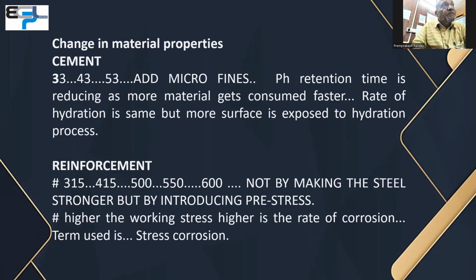There are microfines: microsilica, fly ash, GGBS, and many other kinds of additives. Now, pH retention time is reducing as more material gets consumed faster. Why? Because we are using finer material, more of the surface area is available for hydration in a shorter time. So if you are putting 400 kg of 33 grade cement, and complete hydration takes, say, 60 days, then for 53 grade the same thing will be done in 15 days. So more material is being consumed, and therefore pH retention time is also reducing.